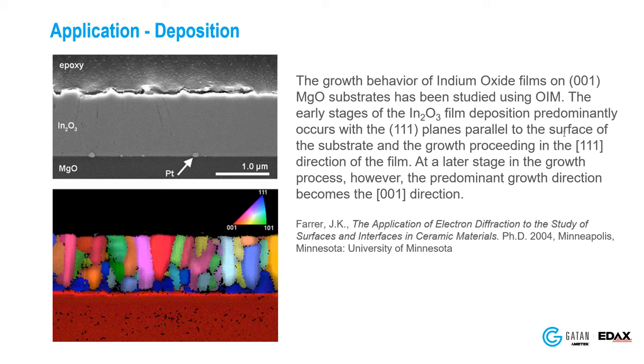Question: How extensive is the database for phase identification? We have our own database with about 500 phases in it. If you're really doing phase ID on something truly unknown, you'll need to use a large external database. The one we work with most is called the PDF-4+ from the International Centre for Diffraction Data, which currently has over a million entries. Phase ID has somewhat fallen out of widespread favor, and we'd love to see more interest and feedback on how to improve those capabilities.